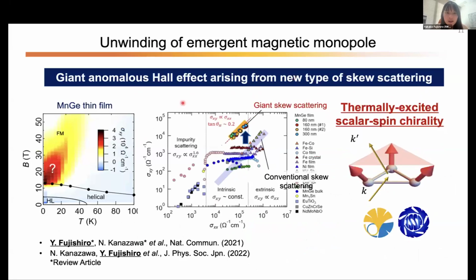textures. And another interesting phenomenon we observed in this magnetic monopole system is that in a single crystal thin film, we observed a very large enhancement of the anomalous Hall conductivity. So this is a very famous plot for the anomalous Hall conductivity with various mechanisms, and it typically shows a general scaling relation. But what we find is that the large anomalous Hall effect observed in this compound largely deviates from the conventional scaling, and we proposed a new mechanism of skew scattering, where the electrons are scattered from the thermally excited scalar spin chirality.